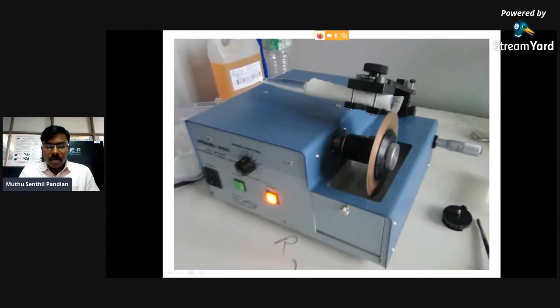Now, how to cut the crystal from the SR method grown crystal? So this is the as-grown 15 centimeter long TGS crystal grown by this SR method. Using this diamond wheel cutter, we have to cut very slowly and very carefully. Ethylene glycol is kept inside the tray in order to avoid any thermal stress in the grown crystals. So this is the speed controller.